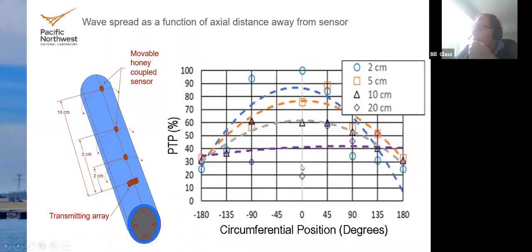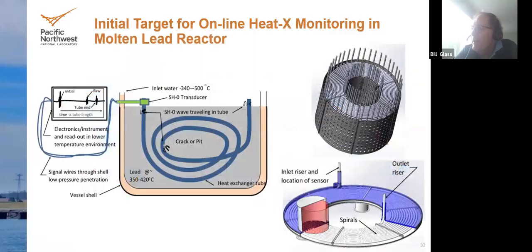And here you can see that at 2 centimeters, we still have some change in the sound level, but as we go to 20 centimeters, the sound level or the acoustic energy is relatively flat all the way around the tube. So a small array can fully cover the tube after it gets up to 20 centimeters away from the sensor elements. So that was pleasing. One of the studies that we have done in order to qualify that kind of thing.